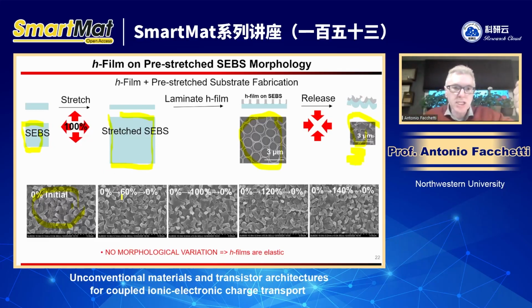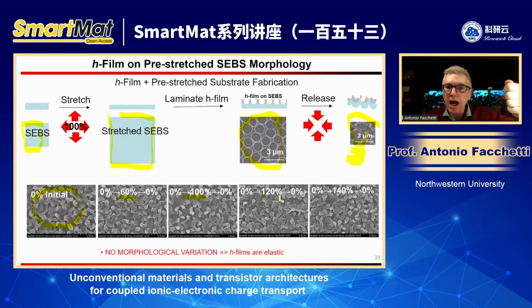We stretch at 60% and go back to 0, then 100%, 120, 140. You see here that if you look at these SEM images, they are identical. It tells you that there is no morphology variation. So the honeycomb film on top of the pre-stretched substrate is elastic. There is no variation in the morphology.